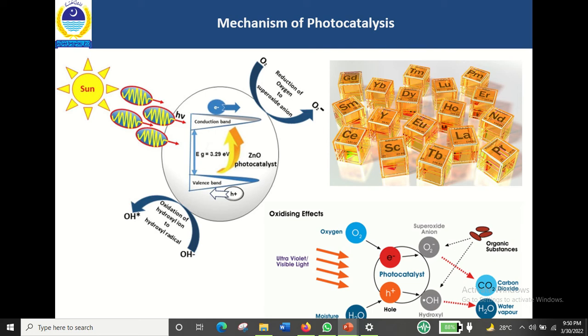The greater ionic radius of rare earth ions compared to ZnO ions is expected to cause lattice distortions in ZnO and some distortions in the structure, which can increase the lattice constant and hence reduce the zinc oxide band gap energy, making it suitable for the visible part of the light spectrum.